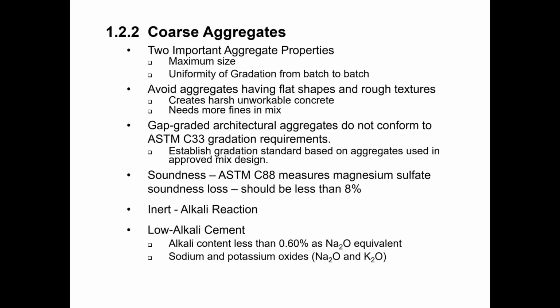Generally, the rougher the texture of the coarse aggregate, then the more fine aggregate we're going to need to get to a workable mix. The more fine aggregate that we use, the more surface area we have to coat, and so that means the more cement and water that's going to be needed in order to get a mix that is functioning the way that we want it to function. Anytime that we're adding cement to our mix, then that increases the cost. So ideally, we want to have well-textured aggregates that interact and interlock with each other over a smooth gradation curve. That will help to minimize the amount of cement that we need to use in order to achieve the desired level of concrete strength.